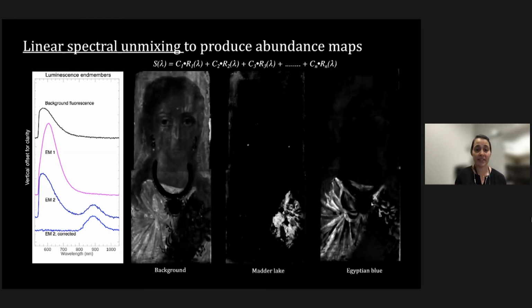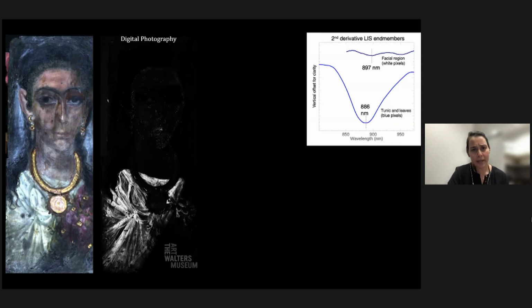So here we can see the effects of the background, but we also now see where Madder Lake is being used, which is much more clearly seen in the earrings and her garment. But now we see the presence of Egyptian blue throughout the tunic and throughout some of the green leaves. And in fact, when we compare it to the photograph taken by the Walters Art Museum, we see that it actually maps the tunic very well. And also it does a better job of mapping Egyptian blue in the green leaves.